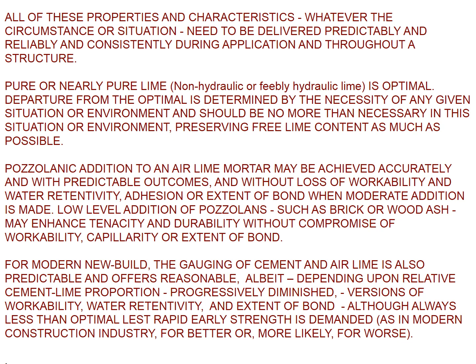Pure or nearly pure lime, which is to say non-hydraulic or feebly hydraulic lime, is optimal. Departure from the optimal is determined by the necessity of any given situation or environment, and should be no more than necessary in this situation or environment, preserving free lime content as much as possible and as high as possible in the conditions. Pozzolanic addition to an air lime mortar may be achieved accurately and with predictable outcomes and without loss of workability and water retentivity, adhesion or extent of bond when moderate addition is made.